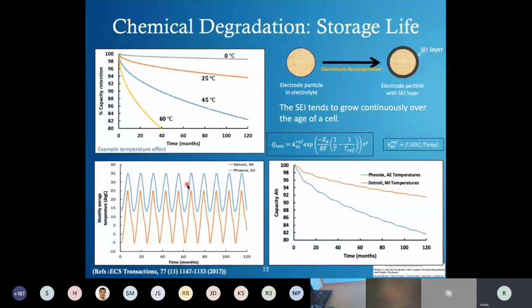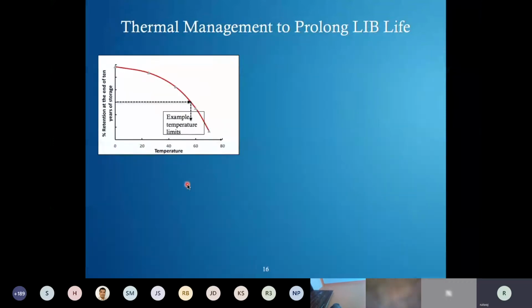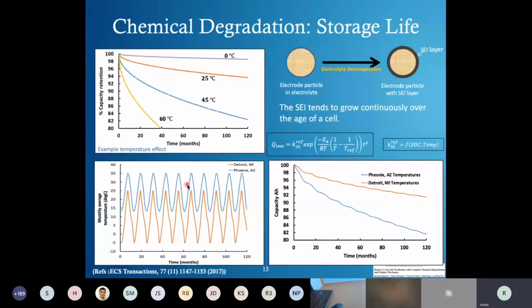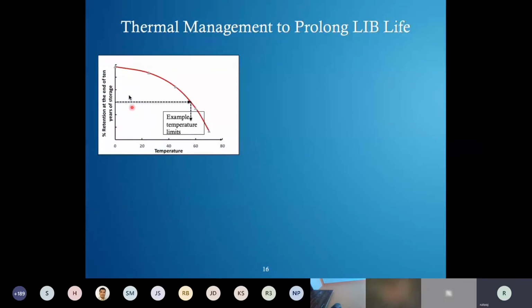Whereas in real life, your cell would have additional heat generation when you're using it. It may have a longer thermal constant, so it may take long to cool down. So the cell temperature could be very different from the ambient temperature, and you'll have to look at the cell temperature rather than the ambient temperature. The important aspect of this understanding is that you will get different life when you are using your cells at different temperature conditions. And this could be used to find out what temperature limit you would want for your system when you are designing your thermal management system.